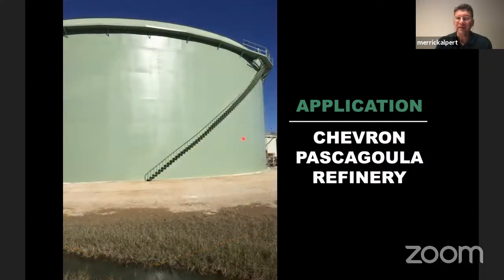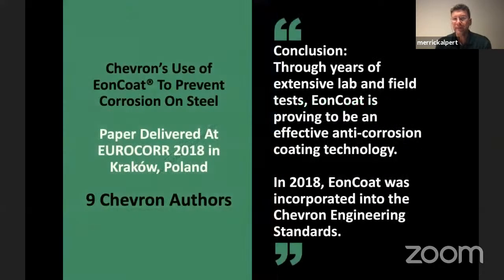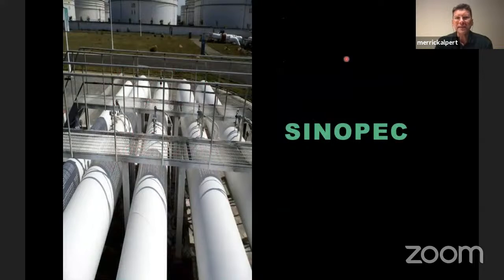And if you drove by that tank, well, on the first day, you wouldn't know any difference. But years and years and years later, you would, because of course, this tank will not corrode, but the tanks around it that have regular paint will. This process is the same, whether we're spraying a tank or whether we're spraying a pipeline or an offshore platform. This is one that we did recently for Sinopec in China, for example. Again, the same equipment, the same coating that's being sprayed onto that steel.